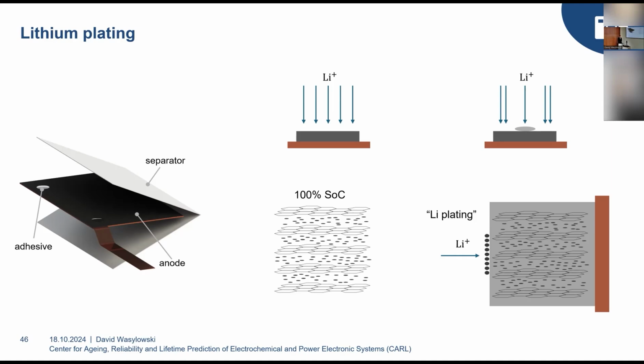But this effect is not only interesting for people who want to design cells, but also for people who want to design fast charging processes, because you can imagine if you are not only locally fast charging your cell, but homogeneously fast charging a pretty homogeneous cell, the first instance of lithium plating will probably happen at the smallest possible inhomogeneity within your battery. So if we are in fact able to visualize this lithium plating with our ultrasound method non-destructively, this would be a great benefit, because there isn't really any method on the market that can do this small lithium plating detection, which is also only happening locally.